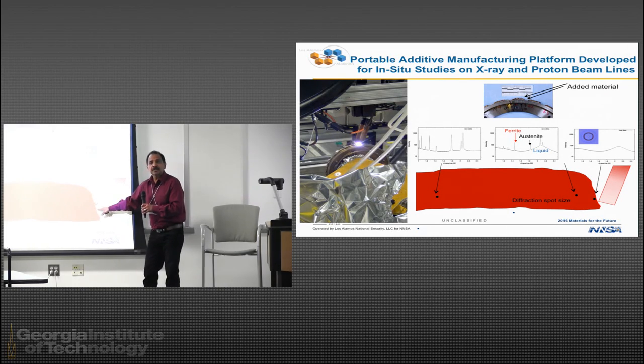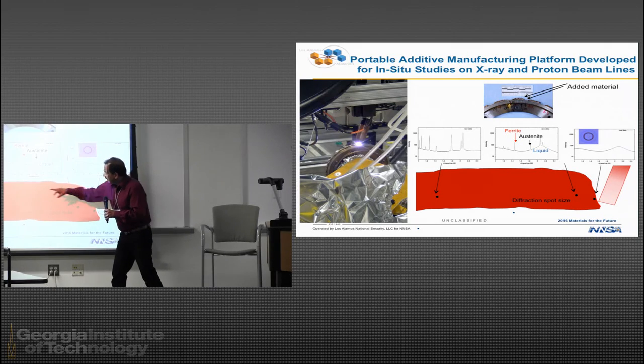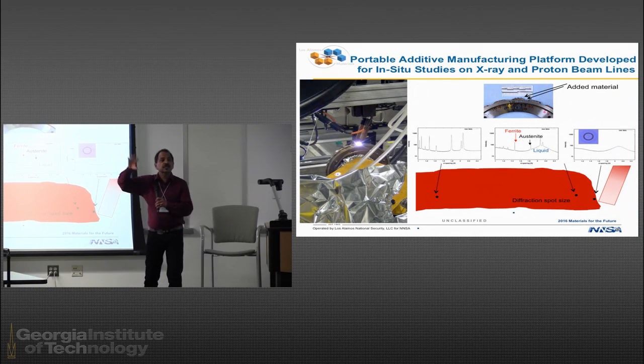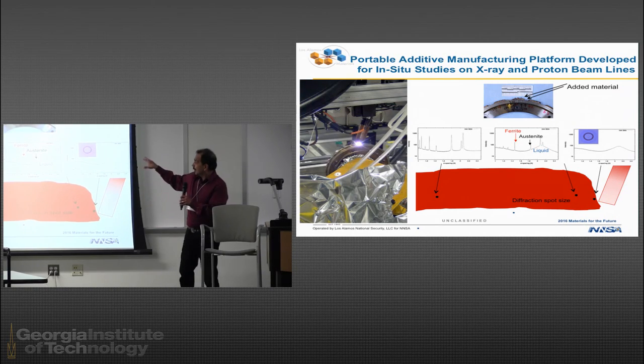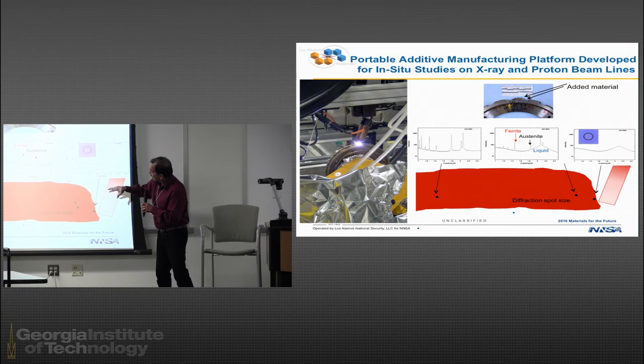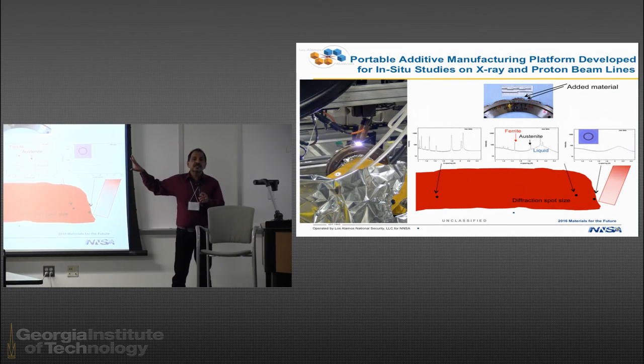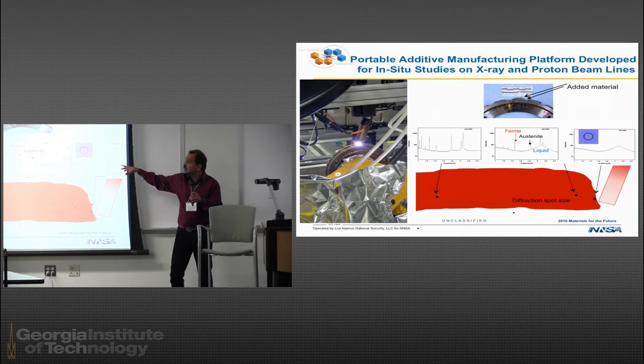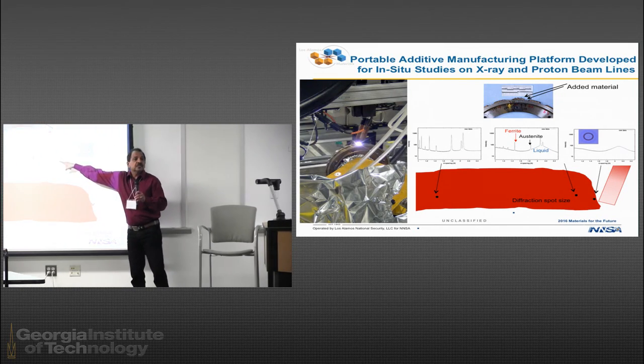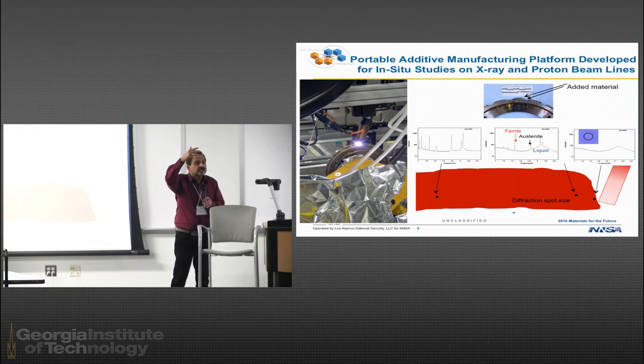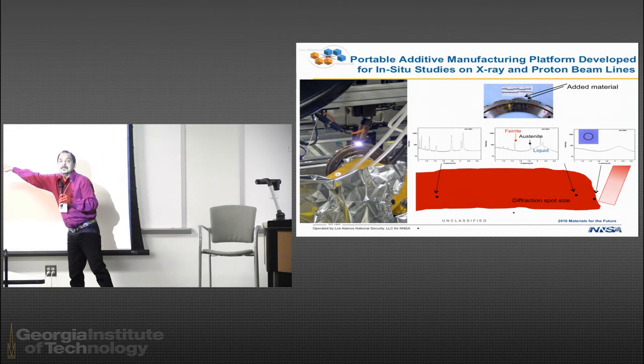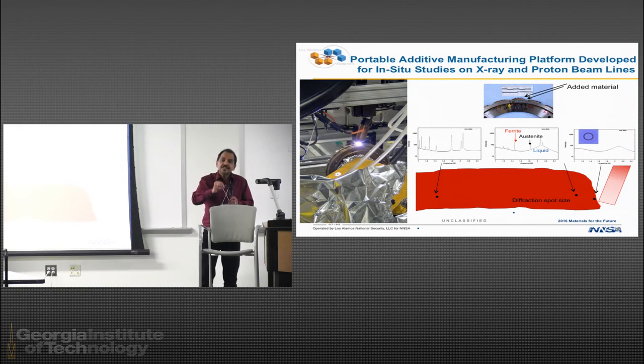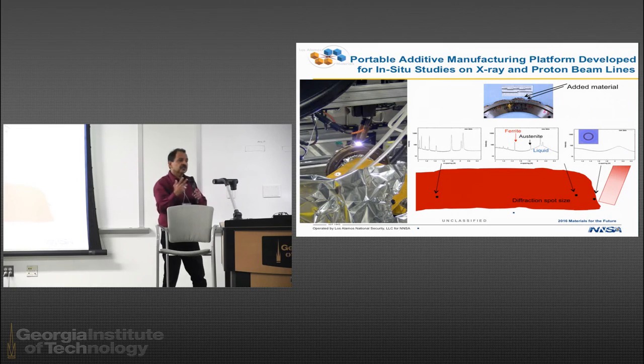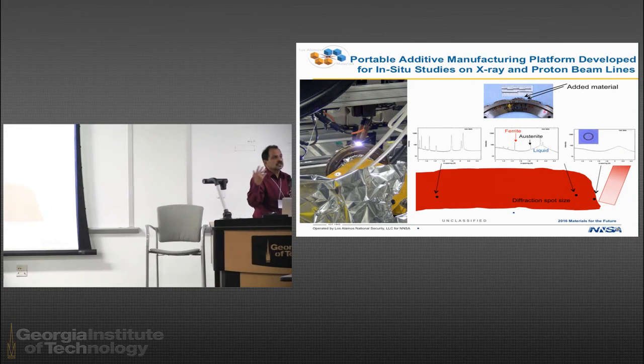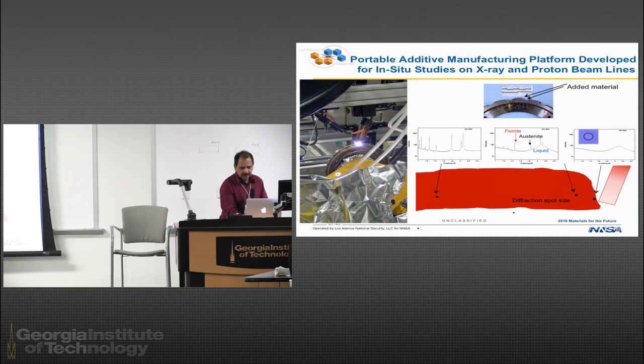So what you're doing is you've got a diffraction spot here, you've got another diffraction spot here, a diffraction spot here. These are the diffraction patterns associated with the process. And so you can see here what's happening is it's essentially molten liquid. It's very diffuse. As you go a little bit here, you're starting to see some of the peaks, the signatures of the crystallization process. And then thereafter, you see well-defined peaks, okay? So it's in situ monitoring of the diffraction patterns from which you can infer things like residual stresses and so forth. So this is a nice example of what we can do, and clearly the data sets are fairly large.